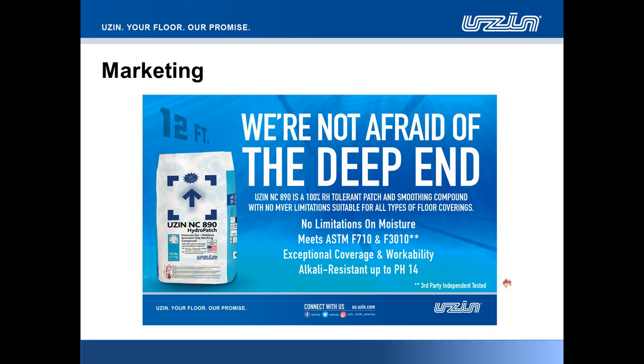And we're proud to say now that we have a formulation that meets the ASTM standards, which are standard practices for installing resilient floor coverings and also installing moisture mitigation systems. Those are respectively F710 and F3010. What those standard practices call for is that the substrate is over 3,000 psi at 28 days. That's the requirement. And our product, NC890 HydroPatch, reaches over 3,000 psi at 28 days and keeps slowly building strength. We have not seen a downward trend. It just keeps getting stronger. The line flatlines over the long term.